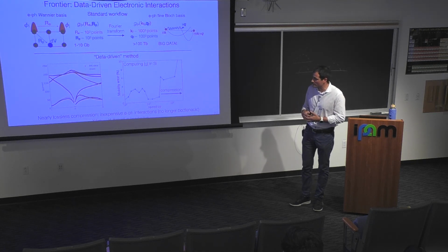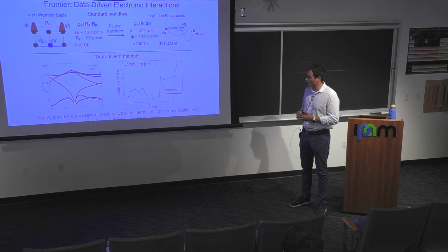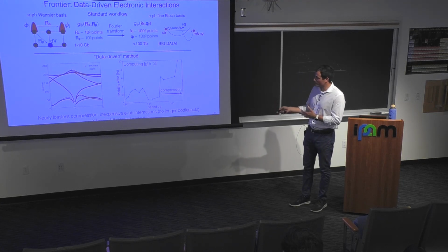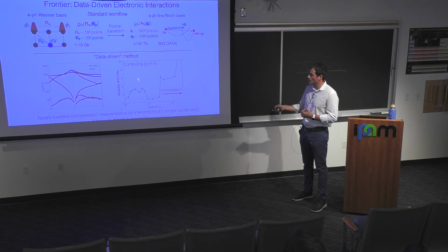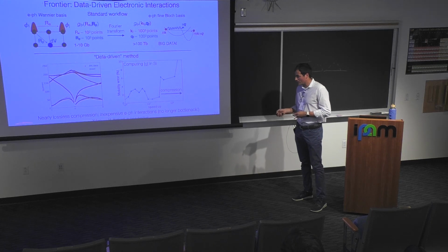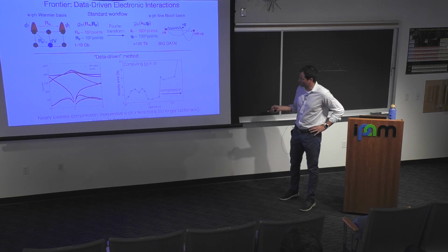So I think there is really great room for further improving these methods, compressing them using these new tools. Well, in some cases, these are old tools, but these methods are now becoming more relevant for first principles calculations. And so if these methods were to work, potentially you would need to revisit all the existing algorithms. And in particular, even for this simple calculation, the bottleneck has always been this interpolation and getting these matrix elements on the fine grid. Now we can show for this calculation that this is no longer the bottleneck with this compression by about a factor of 100. And so there is hope to find more of these nearly lossless compression algorithms.